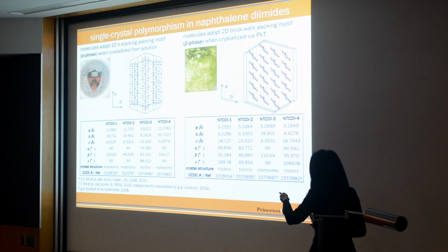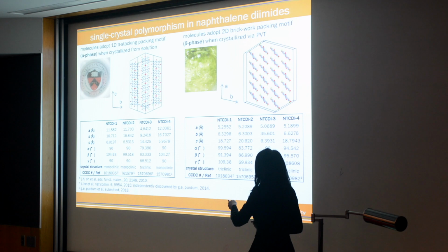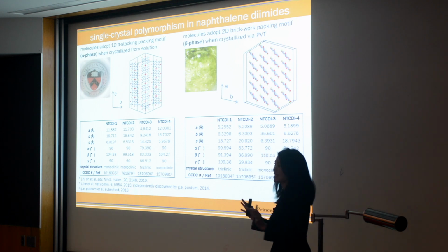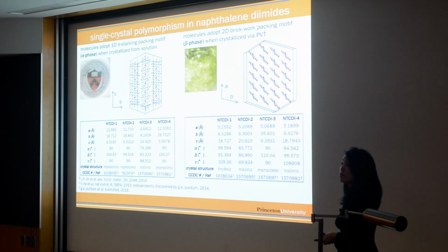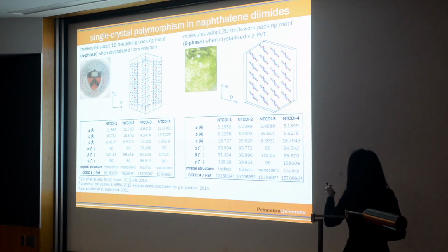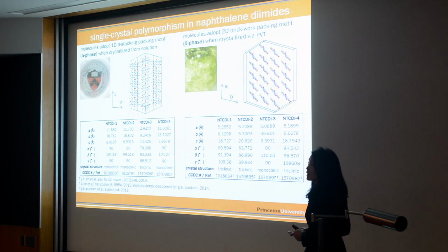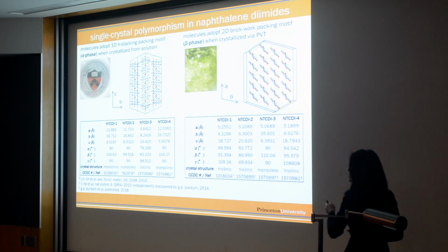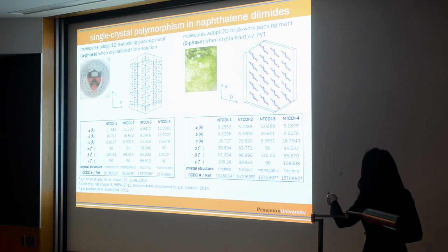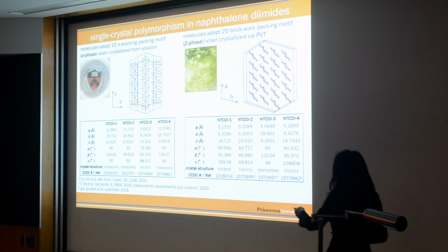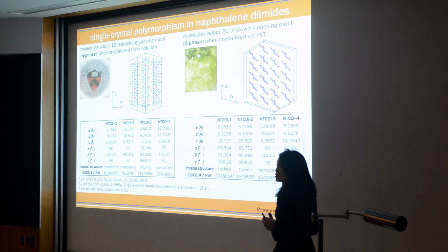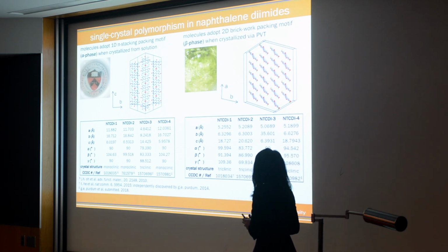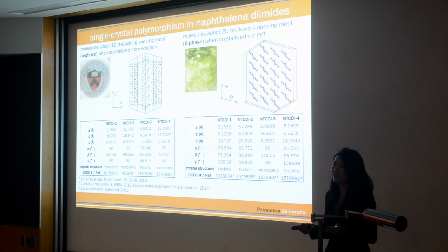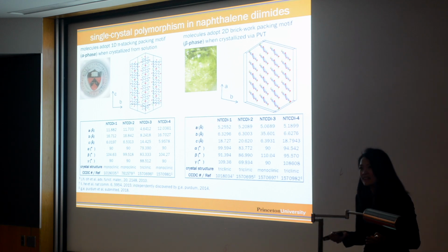If you grow them from solution, you access this one-dimensional pi stacking motif that we call the alpha phase, and the crystal structure is shown here. These are the unit cell dimensions. Don't worry about it too much. Suffice to say that we have it. Now, if you grow it by physical vapor transport, you access this two-dimensional brickwork packing motif that we call beta phase. And you can see the crystal structure here. Okay, this is 2D because you can transport charge in two directions. Here, this is 1D because you can only transport charge in one direction. So it turns out that these subtle differences in the chemistry of the substituent don't really matter in this case.